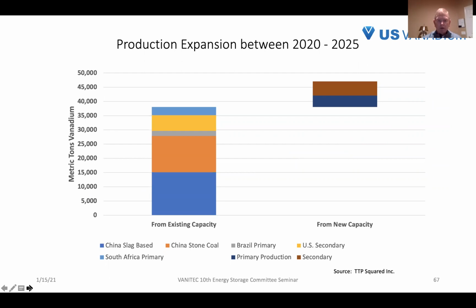The majority of this increase will come from existing capacity that's out there. If you look at this chart, you'll see the blue bar on the left-hand side, China slag-based. There's actually a lot of capacity for the Chinese steel mills to increase vanadium slag production and therefore to increase vanadium production. There's a couple of very large blast furnaces that have had trouble getting up and running over the last few years. And we're projecting those blast furnaces will get up and running and generate a significant amount of vanadium.